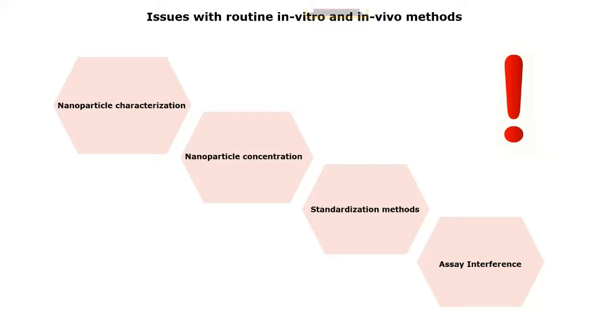Since in that case, you take into consideration both the particle size as well as the number, and both of them are contained in this matrix, because the toxicological response depends on the surface properties, which is known, and the surface area exponentially increases with the decrease in nanoparticle size. So if you take into consideration surface area per volume, then that gives you a very good idea of how you should express your nanoparticle concentration.